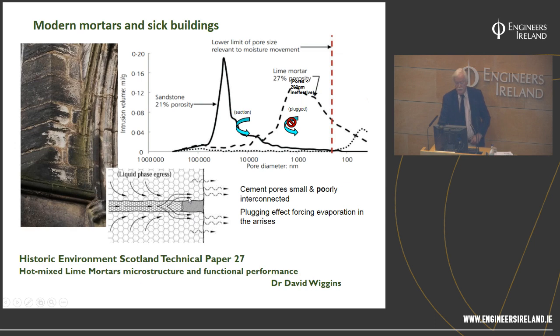on the pointing, a replacement pointing mortar. This is again using a sandstone, where there is a combination of what's known as a siphon effect of your pores that pulls your moisture out, which will always be on the move. And if you specify too hard a mortar, like cement, as a pointing mortar, you will block it, and it'll go over the side, as you can often see in brickwork, and you get spalling, what has happened here. If, of course, it's an impervious stone, it just doesn't go out, it just stays back and makes the wall damp. So if you design a pointing mortar that's not compatible with the bedding mortar, you can have that phenomenon, and it is happening. We certainly know it happens with cement, and now English Heritage have decided it's happened quite a lot with their NHL mortars, where they've been incorrectly specified. Nothing wrong with the material, just wrong with the use.